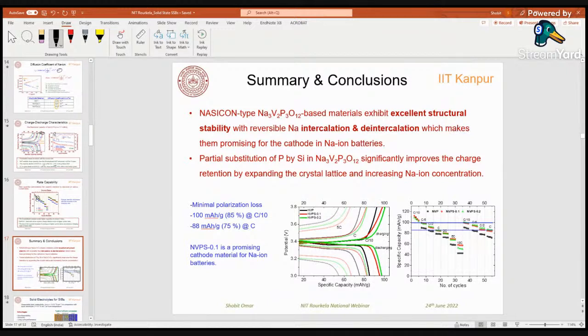Based on this, I can summarize that NVP is an excellent structurally stable cathode, and its capacity and electrochemical performance can be improved by doping phosphorus with silicon, because that will increase the sodium ion concentration and also expand the crystal lattice, which will help the sodium ion to diffuse faster inside the material. So here I talked about the cathode that is based on NASICON. Now let us talk about the NASICON based electrolytes, and that is also ceramic. Finally, we are going to use this NASICON based cathode that we have developed, and also the developed solid electrolyte, and we will see what the performance of the solid state sodium ion battery is.